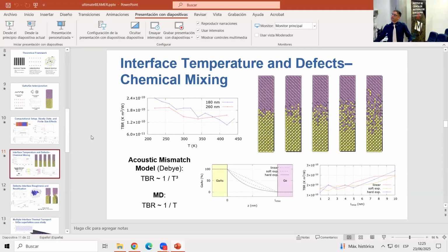Not easy. I would say, here I can just try to provide you with a general picture. When you are using molecular dynamics, you are including phonon processes at all levels, whereas in the acoustic mismatch model, you're not considering interactions between the phonons at all. That's basically the model: free, non-interacting phonons. So probably phonon interactions kick in.